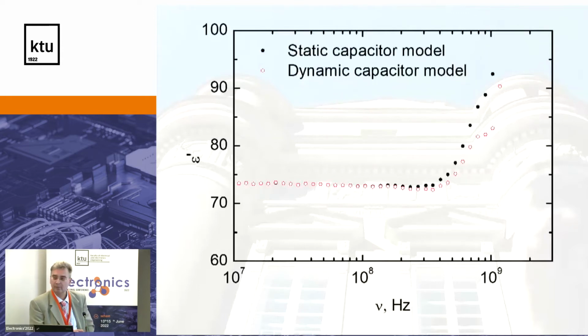If we use the simple static capacitor formula, it's the black points, results at above 700-800 megahertz going up. This shows the formula. Is it true? The answer: it is not true. It is fake. It's due to non-homogeneous distribution of electric field, and we apply the formula in a place where we cannot apply it. It's not working. So the dynamic capacitor with Bessel's functions shows a little bit better. You can extend by 100 megahertz or so, but not so much.